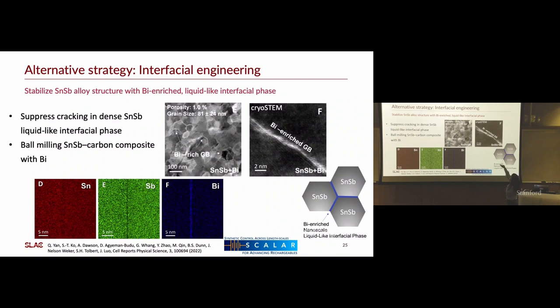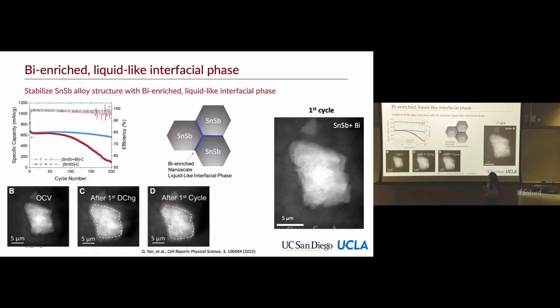And so you can see on that cryo-STEM image, bismuth is really sitting at the grain boundaries between the crystals. You can also see that here in the EDS. And so this ball milling was believed to help the cycling. So they saw that electrochemically, it was cycling better, but we wanted to also see that and confirm it with the X-ray microscope. And so here you can see the electrochemistry.